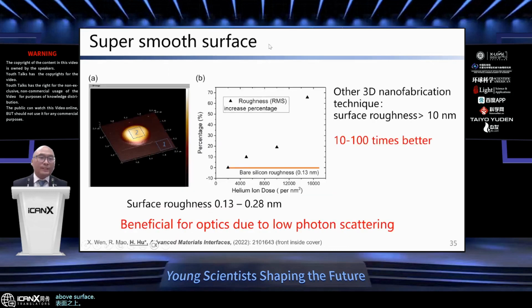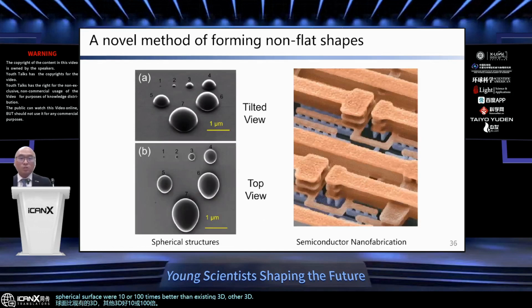One very important characteristic of this swelled silicon is that it's super smooth. We measured the surface roughness using AFM. The bare silicon wafer we used is 0.13 nanometer. After swelling, the surface still has 0.28 nanometer. It's about a few atoms of roughness. In terms of roughness for a 3D spherical surface, we're 10 or 100 times better than other existing 3D nanofabrication techniques. This is a comparison with conventional semiconductor nanofabrication, thin film deposition. You can at least make some grayscale spherical surface, but you can never achieve this super smooth spherical surface.